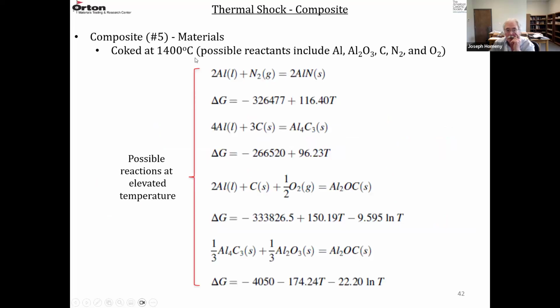So when it's coked at 1400 degrees C, you have different kinds of reactants present. You have aluminum, aluminum oxide, carbon, nitrogen, oxygen. And coking is basically burying the samples in a crucible filled with coke, closing it with a lid, and heating it to heat treat these things in non-oxidizing conditions. So these are possible reactions that can take place.